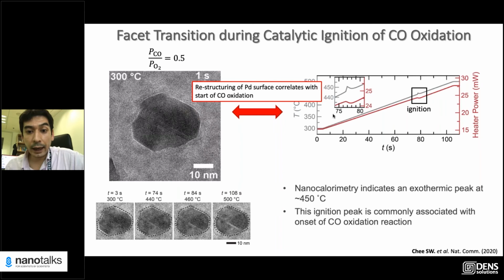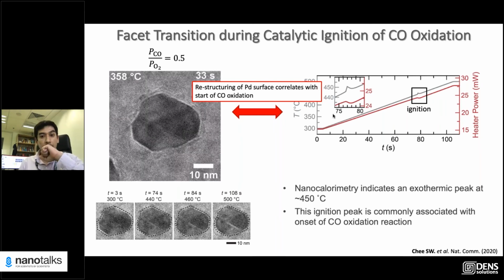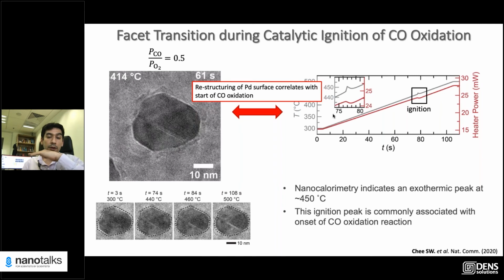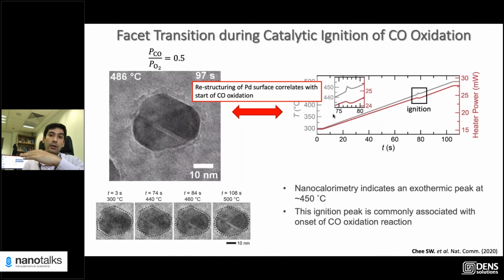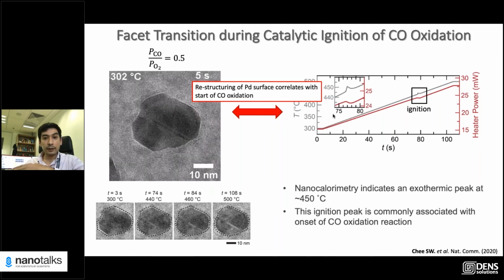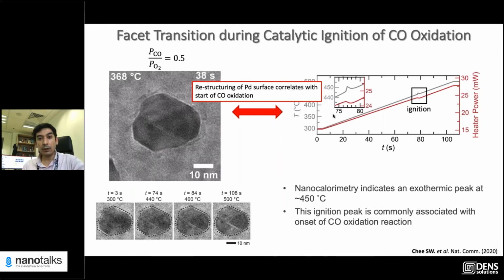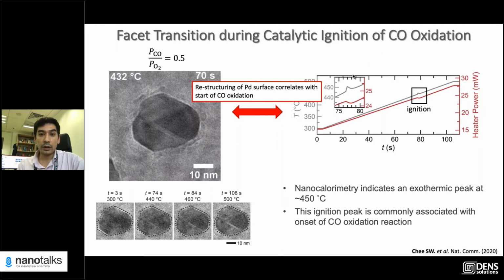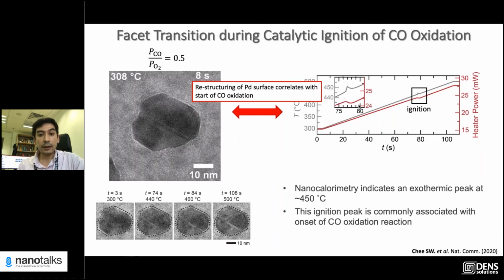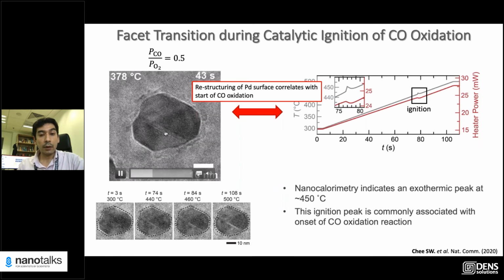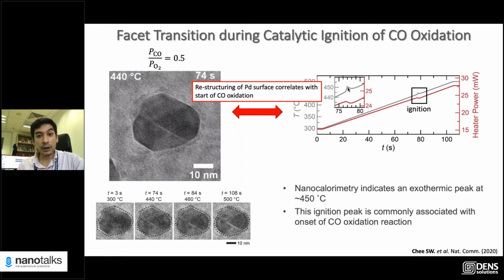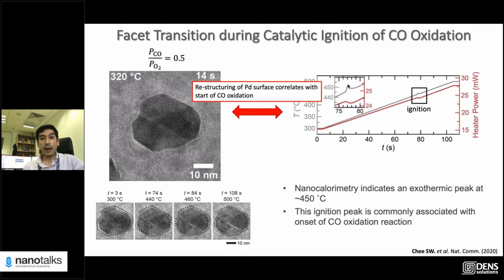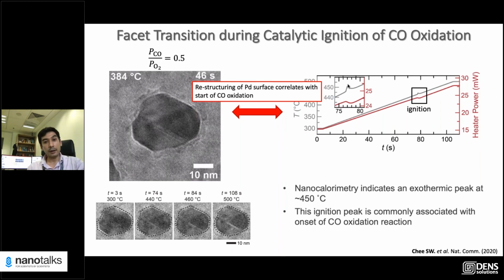So why is this happening? Well, you can treat this as a kind of calorimetry experiment, right? CO oxidation is an exothermic reaction. So as soon as you kickstart the reaction, nanoparticles release heat, and your feedback mechanism dials down. And then you can also monitor the temperature at the same time through these resistive measurements. As it dials down, this corresponds to the point where the nanoparticle becomes active. And since it's an exothermic reaction, you also can read out that the temperature is jumping. So this point is called the ignition point of the reaction, and this signifies where the transition occurs. And right at that point, the structural change happens.